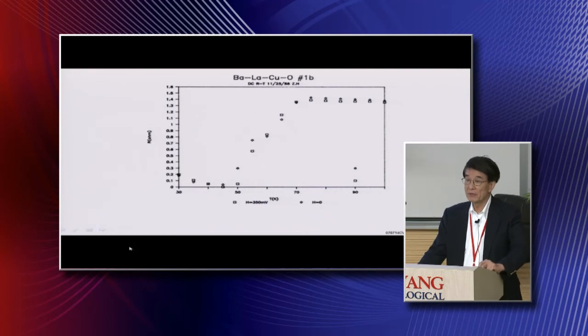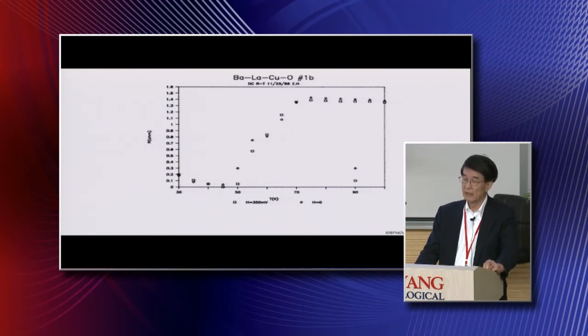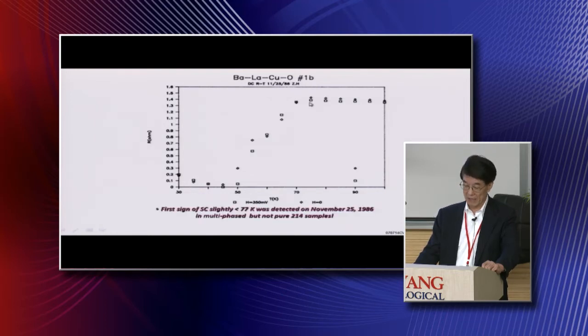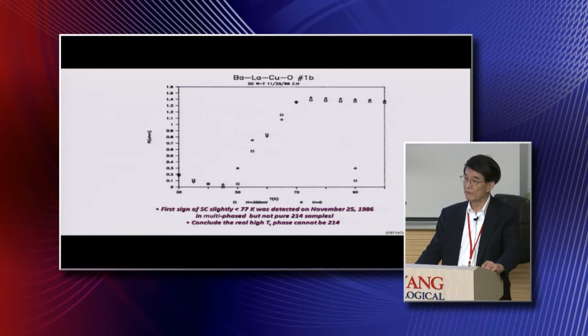Okay? So the reason we were optimistic was back on 11/25, a day before Thanksgiving, 1986. Actually, we already detected the resistivity drops starting at about 70 degrees. And that's why we were so optimistic about it. This turns out to be the first sign of superconductivity, slightly below 77 degrees, detected in a multi-phase sample, but not in the pure 214 compound. The 214 compound was identified by Kitazawa and Tanaka in Japan at the time from Müller and Bednorz's sample.